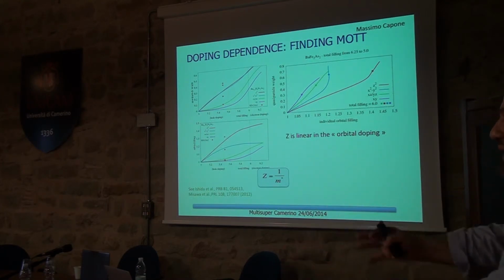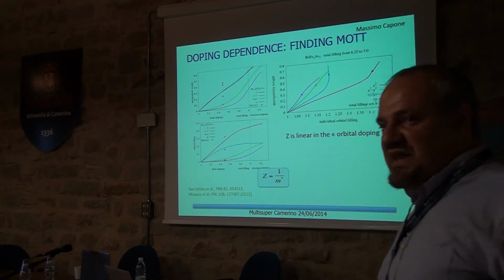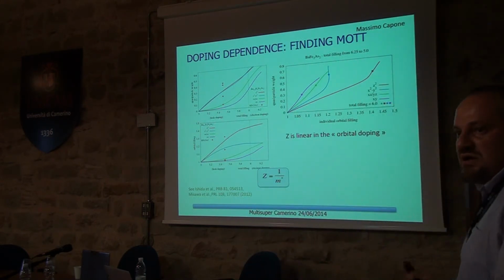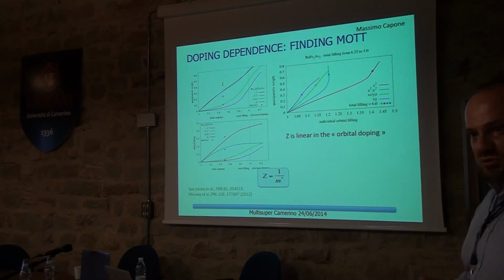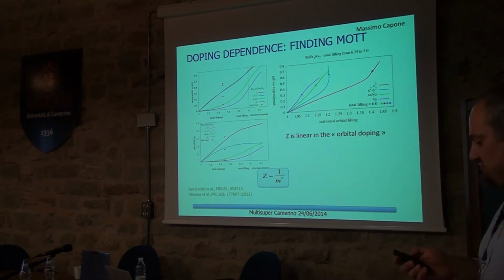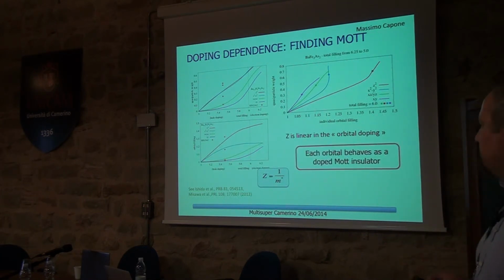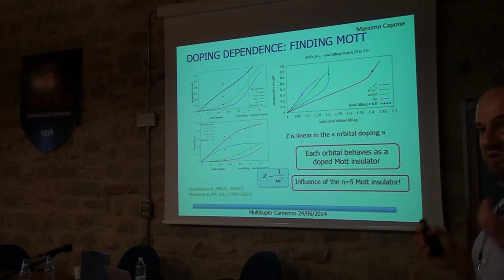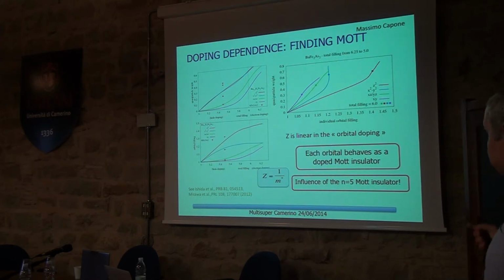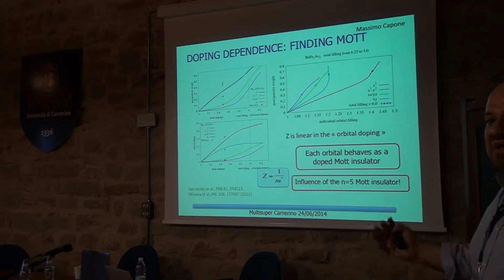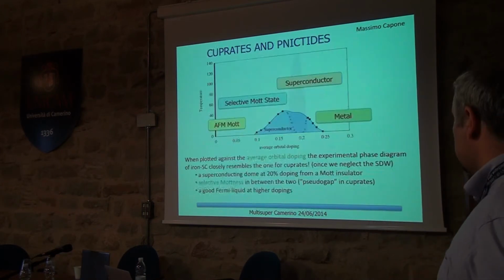You have this whole bunch of m stars and numbers and everything, and this tells you why one m star is large and one is small. And it also connects strongly with the physics of iron-based superconductors, because each orbital behaves now like an individual Mott insulator. And of course, that tells you that this hypothetical material with 5 electrons is our real parent compound, the one which is like the antiferromagnetic parent compounds of the cuprates.